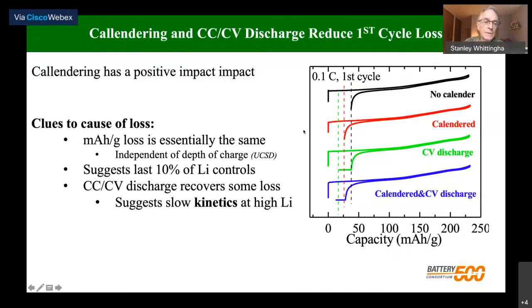But the other thing we can do, on a normal battery, you charge and discharge at a constant current. If after you do your constant current discharge, you then do a constant voltage discharge, as we show here. So this is the green one, come down to the cutoff voltage, then we hold it at that voltage, we can recover quite a lot more of the capacity. If we calendar and do the constant voltage discharge, we get even more back.